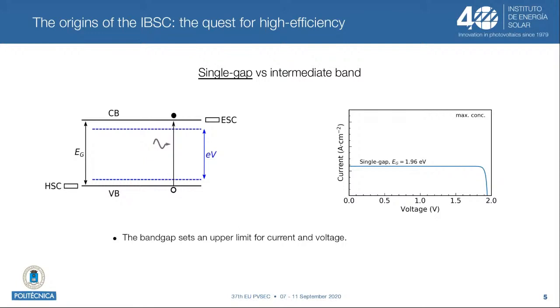And the idea is that by introducing an intermediate band in between the valence and the conduction band, we are able to exploit absorption of photons like this, which have energy lower than the band gap. And with this two-photon absorption, the current can be increased, and we don't have such a high voltage loss. So by combining this increased absorption and maintaining a high voltage, we can get high efficiency. This is what I plot here.